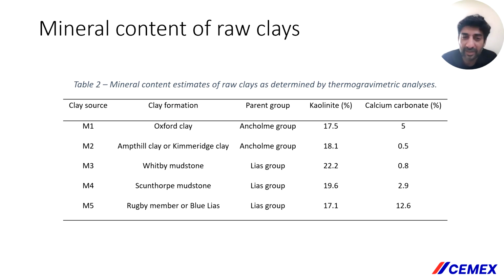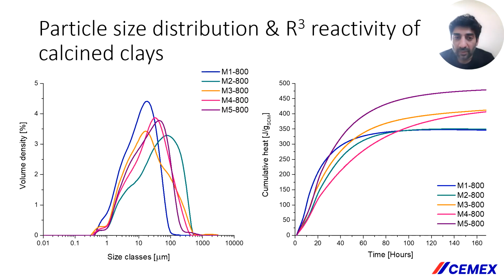Okay, so this table basically shows the mineral content estimates of raw clays determined by thermogravimetric analysis, particularly kaolinite and calcium carbonate contents. Kaolinite contents ranged between 17 to 22%, and calcium carbonate contents from less than 1% up to circa 13%.